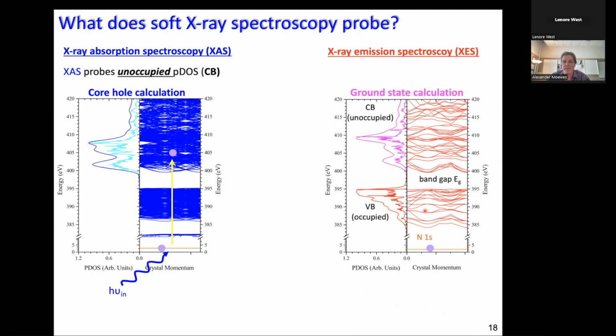What happens now is that the valence band electron comes down and refills this hole, and if, among many other things, predominantly Auger electrons, you have the energy released in terms of a photon. This is called an emission photon typically. You can analyze the energy of these photons, and then you have the density of distributions in the valence band. So what you see: absorption probes the conduction band or unoccupied states, and emission probes the occupied states or valence band. If you have both together, you immediately have the band gap.